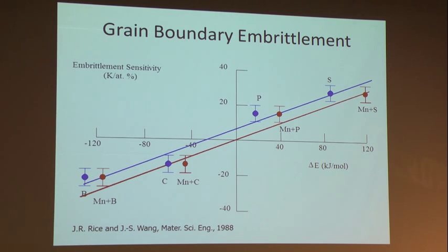Initially, unique to iron, there was enough data to actually test out this correlation that the surface thermodynamics had been measured. We went on from that to then correlate the same quantity to the energy differences that we predict from our DFT calculations, and showed the ability that we could correctly predict the relative embrittlement potency of phosphorus and sulfur and the cohesion enhancing effects of boron and carbon.